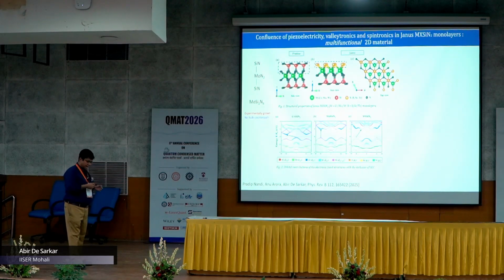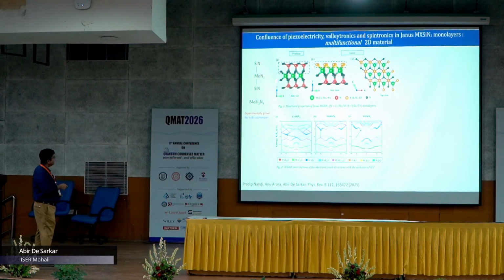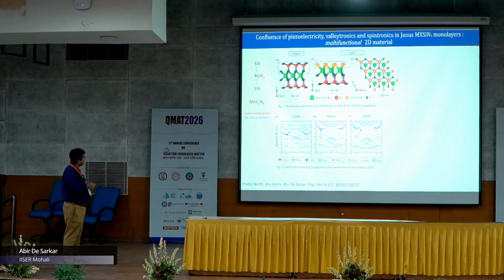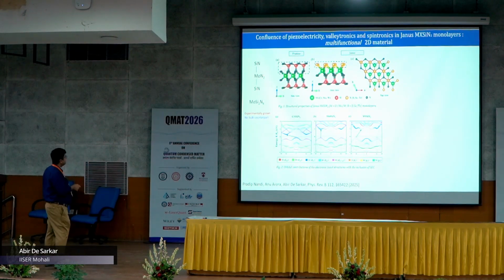And in the interest of time, I will be presenting only these two works of ours in this talk. And now this is a 7-layered structure which has been grown experimentally, where a MoN2 layer is sandwiched between two layers of silicon nitride. It does not have any bulk counterpart. Now, if you replace the SiN2 layer by a layer of chalcogen atoms, you can turn this into the so-called Janus structures, which have been widely studied, at least theoretically.